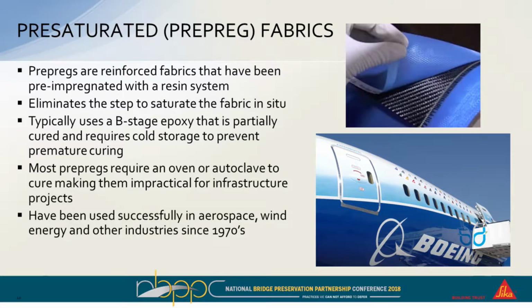Again, the main difference or the advantage of a pre-saturated system is that it eliminates that step out in the field for wetting it out. It's all done in advance. Typically, the resin that's used is what's known as a B-stage epoxy, which is a partially cured resin. Because what you don't want is you don't want the resin to start curing before you need it. It has to remain pliable, and then it has to cure in the shape that you want it to cure in. So what that typically has meant is you have to keep it cool, either in refrigerated trucks, keep it refrigerated right before you install it, and then you have to put some type of heat to it to make it kick off and to cure.